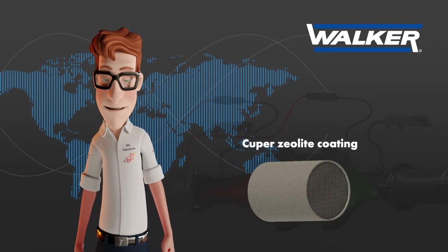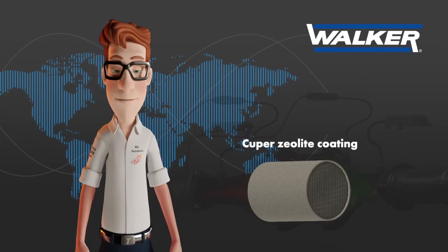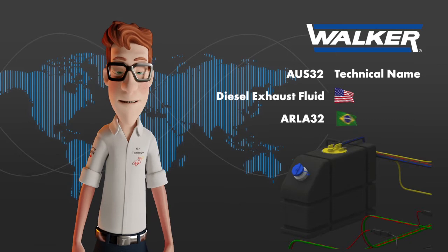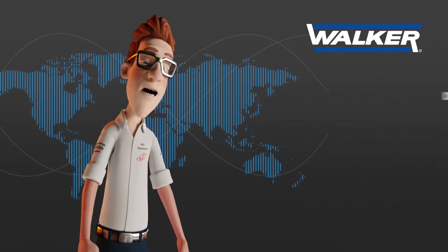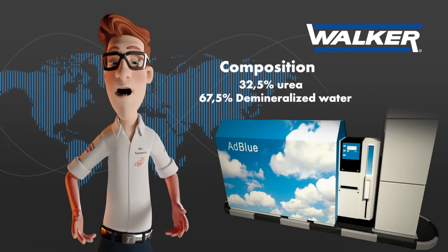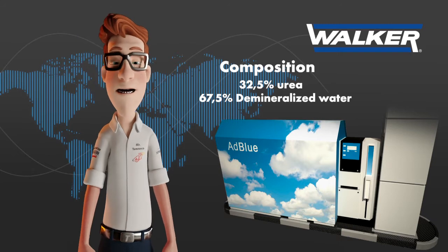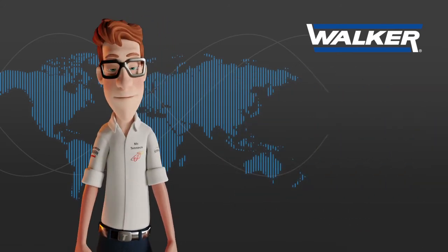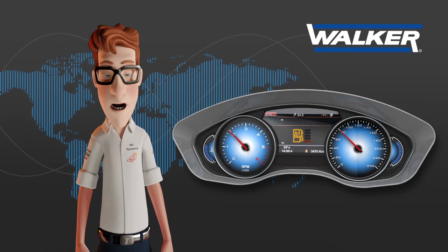The internal ceramic monolith of SCR catalysts is built with a special copper zeolite coating. This unit is designed to work in combination with a reducing additive. These additives have many names depending on the country — in the US they're called diesel exhaust fluid, in Brazil ARLA 32, but the technical name is AUS32. The most common reducing additive is made with a compound of 32.5% urea and 67.5% demineralized water, marketed in Europe under the trade name AdBlue. The amount of reducing agent used is about 5–7% of the fuel consumption. A dashboard light and written message in some models will indicate the need to refill the additive tank when it reaches a certain limit.